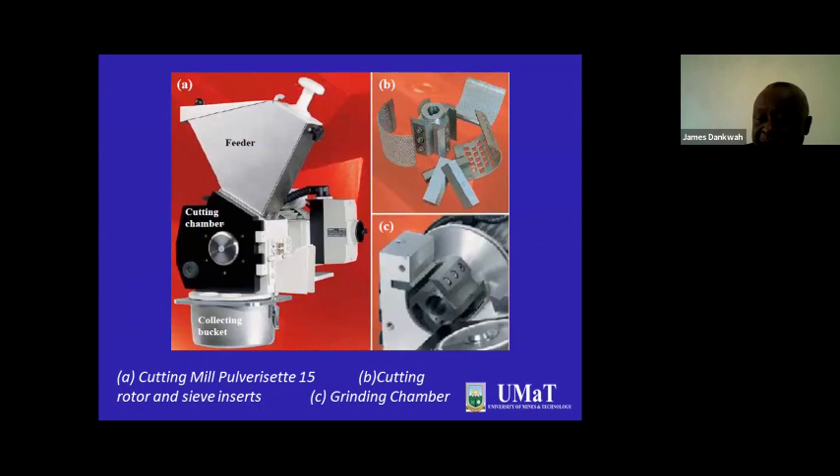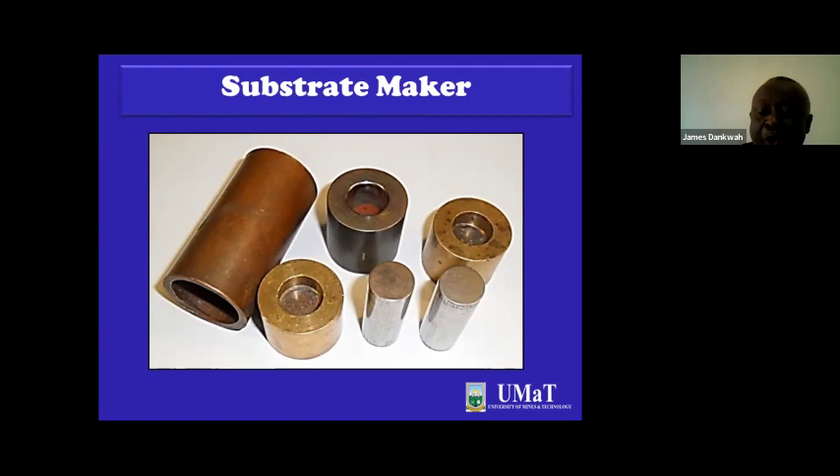So we get our powders — our pulverized carbonaceous material — whether by charring, heating and embrittlement, or by immersing plastics in liquid nitrogen in a cryogenic process, which also makes them instantly brittle and easy to break. Once you have your powder, regardless of the route taken, you can mix your pulverized carbonaceous material with your pulverized iron ore, form pellets, and you are ready to do reduction to produce your metallic iron.